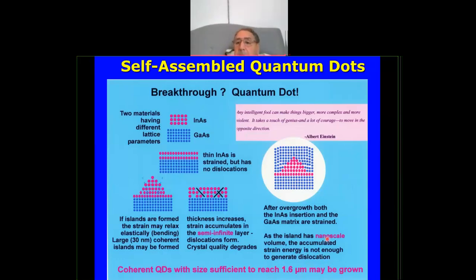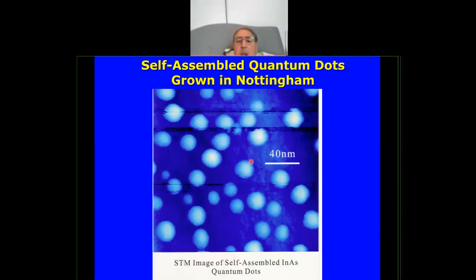So that's extremely important. Now, let me show you a scanning tunneling microscope image of these self-assembled quantum dots, which we grew a long time ago in Nottingham. You can see these islands. Sometimes the sizes can be different, but you can control the size distribution; this just gives you an idea. One thing you can notice here is that because they are self-assembled, they nucleate wherever they like. But there are techniques we can use to order them both laterally and vertically by playing some tricks to make all these dots really regular. Especially if you want to make quantum computers, you want to access those quantum dots at the right position. But this is just one of the slides to show you how these quantum dots look.